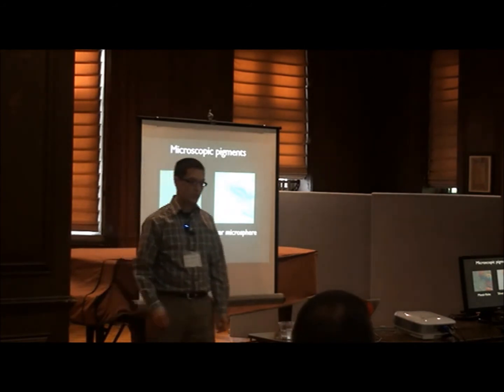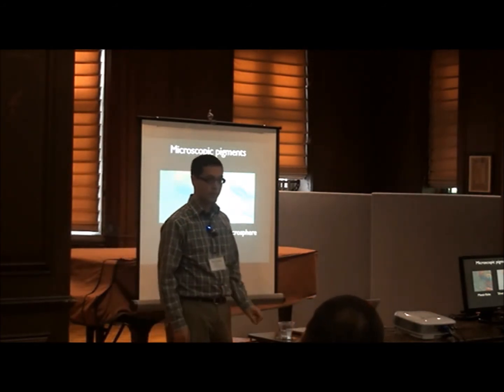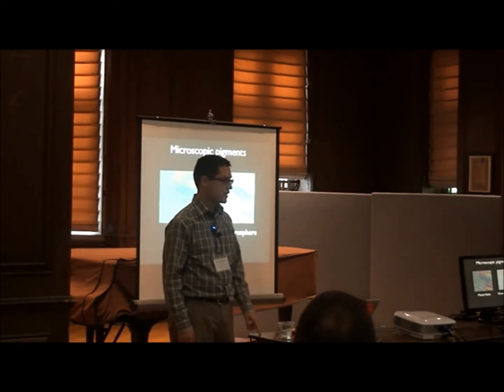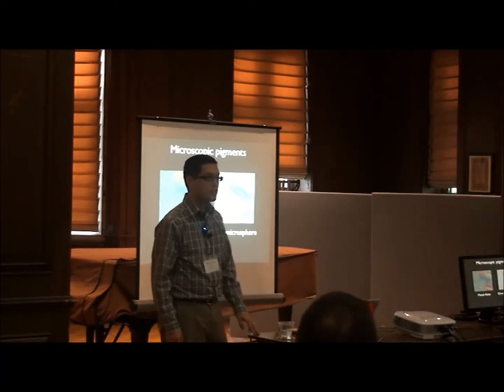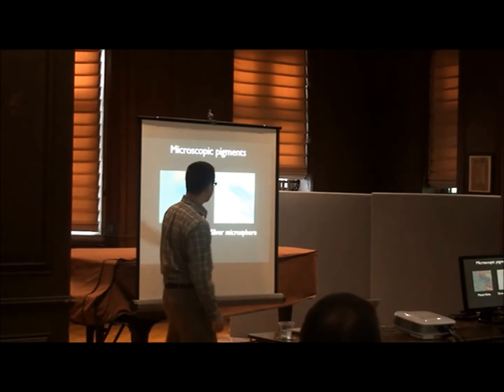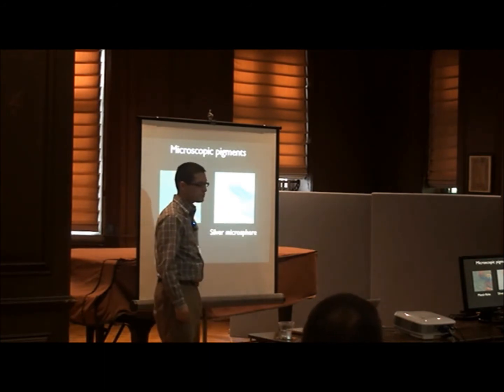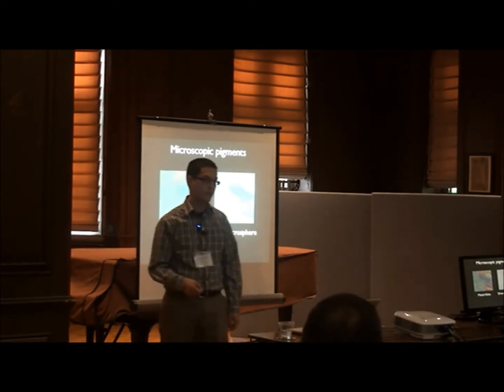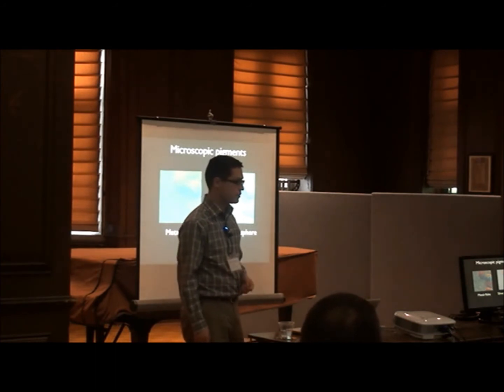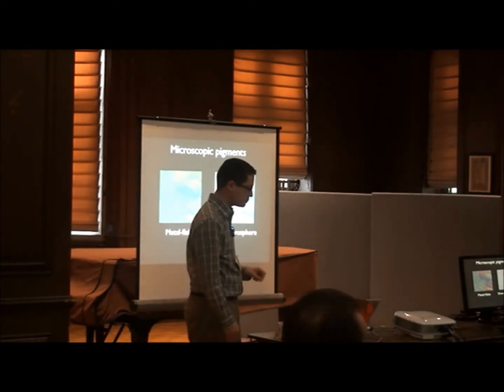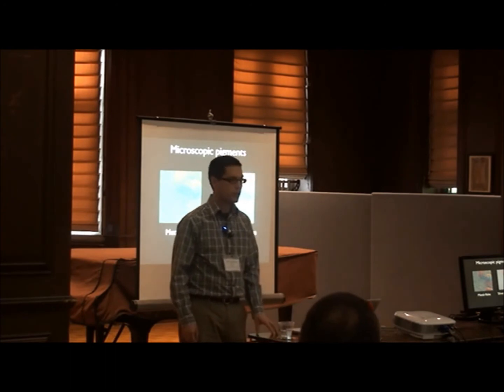However, when we replace those metal flake pigments with silver microspheres, average particle size 500 nanometers, you no longer see them. And so we can get a much cleaner image here. And it's because that particle size is smaller than the pixel size of our camera, or what we're resolving. So that was a simple hardware change.